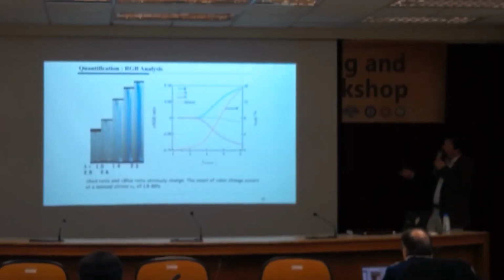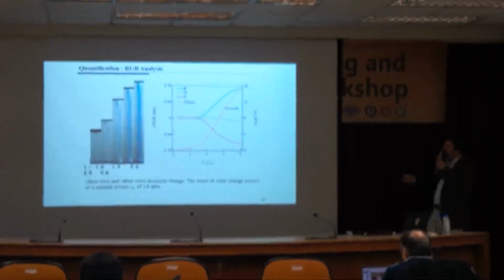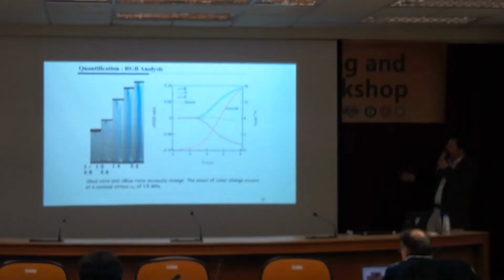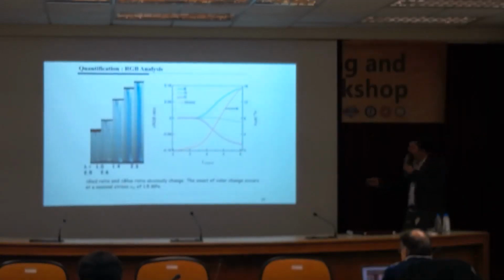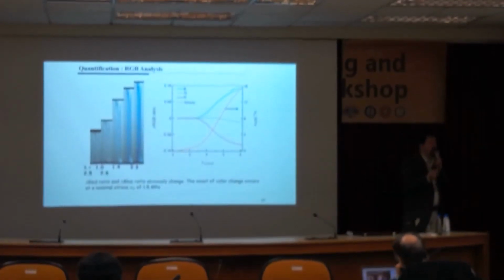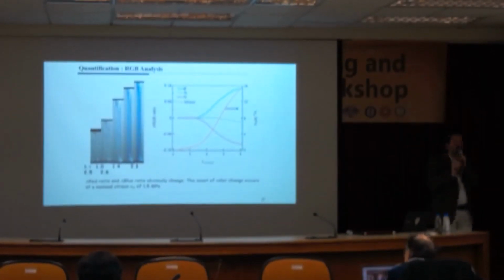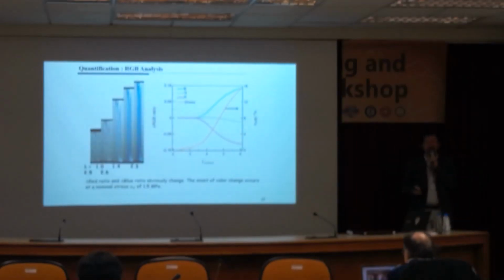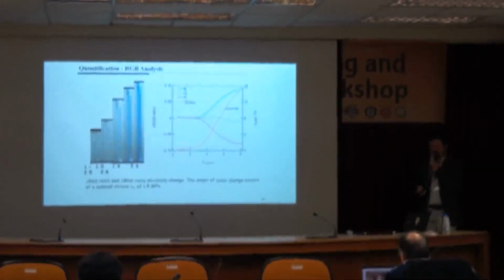So here what you see is the color change, and then you see in yellow the actual stress. The measure of the stress can be made after a certain threshold, because you have no signal below this point, no signal below 1.5 megapascal in this case, but this strain hardening material gives you a definite direct signal of the stress. It turns out that, of course, what you're detecting is a concentration of activated molecule. The molecules are distributed randomly, this is statistical, but the average concentration of activated molecule depends on the stress.